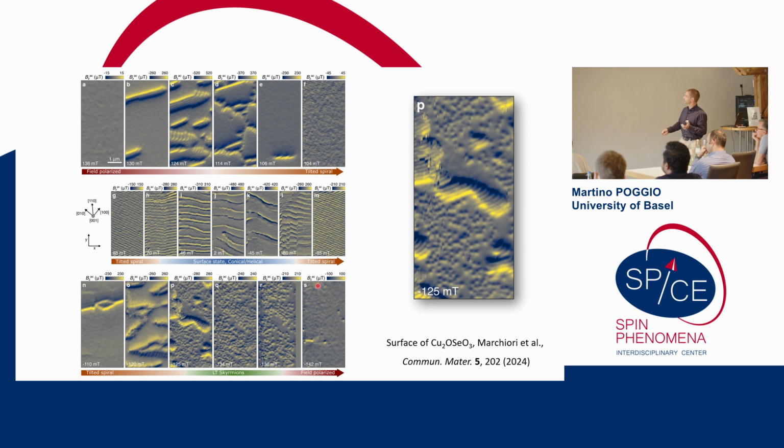There's a lot of things that you can get from this image that you can't get from, let's say, a bulk neutron scattering image that essentially averages over the entire bulk of the sample. And here, for instance, in this transition between phases, we actually see coexisting spin polarized phase, conical phase, and skyrmion phase all together. And there are some quite complicated domain structures here that we still have to understand, that in a common bulk measurement would just be averaged over.